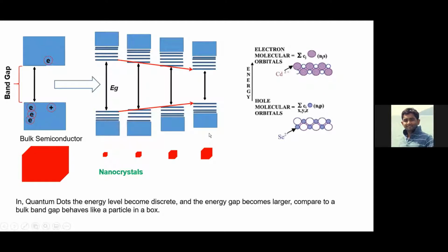That means you are getting the red part of the spectrum. So when you have a smaller box, the length is small, and you will have a higher emission. You can see here it's the opposite, inversely proportional to the length, and you can see when the particle size increases, the band gap decreases, and you can go from the blue part of the spectrum to the red part of the spectrum.